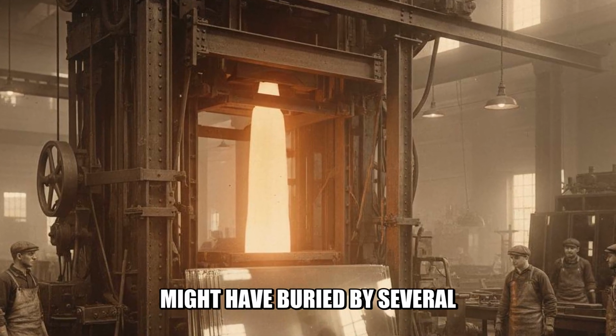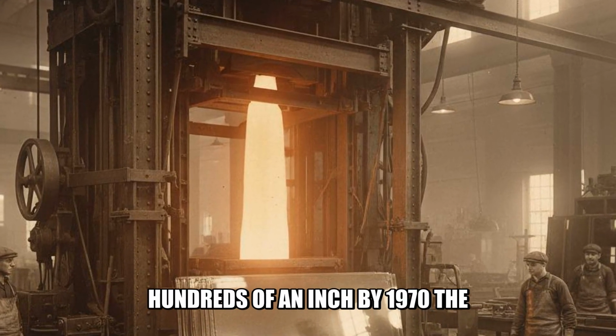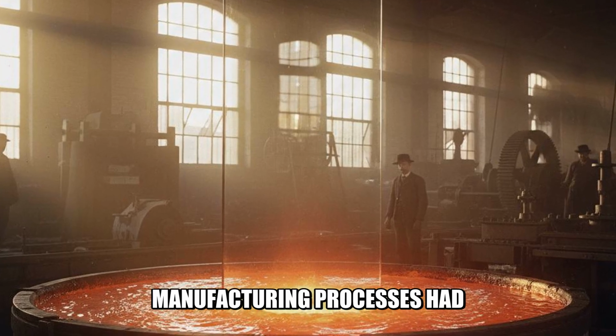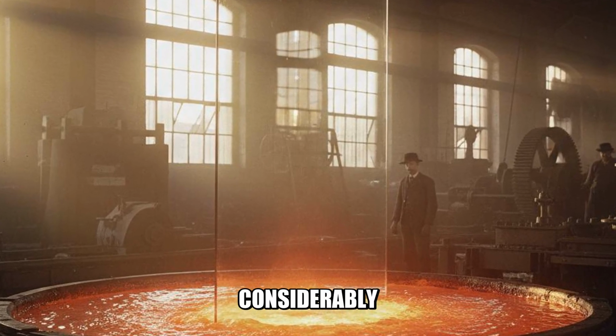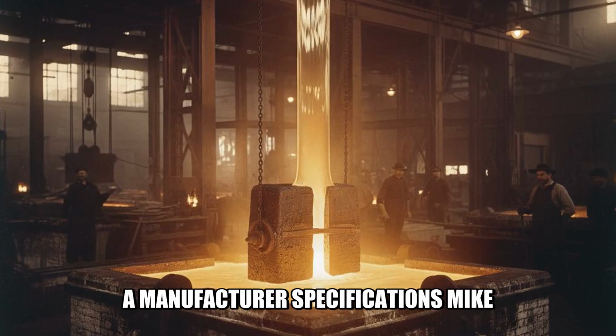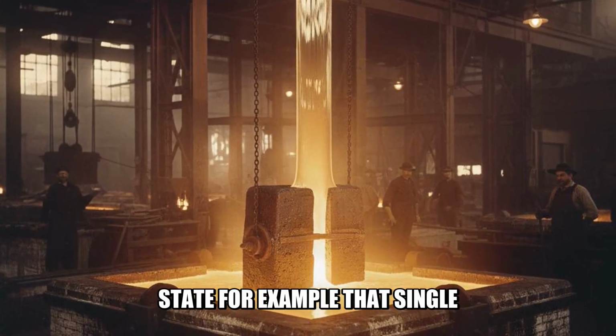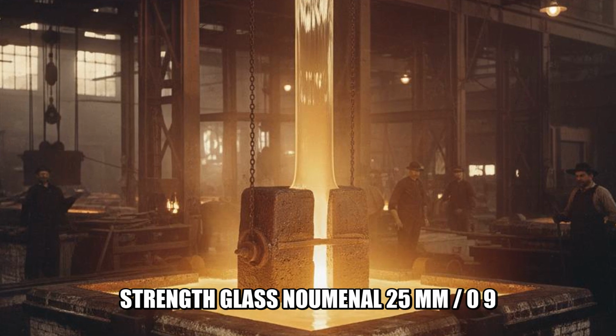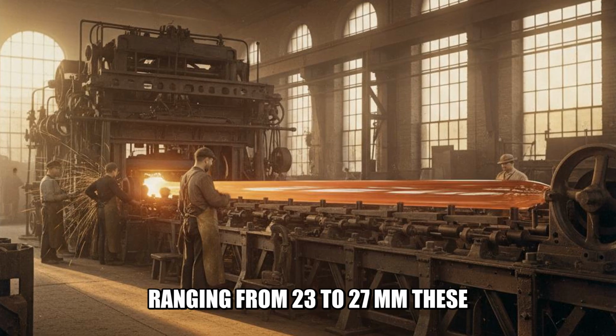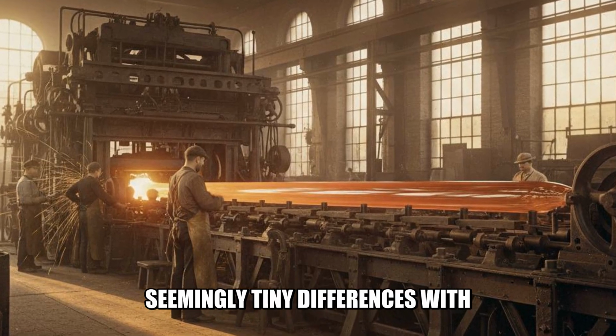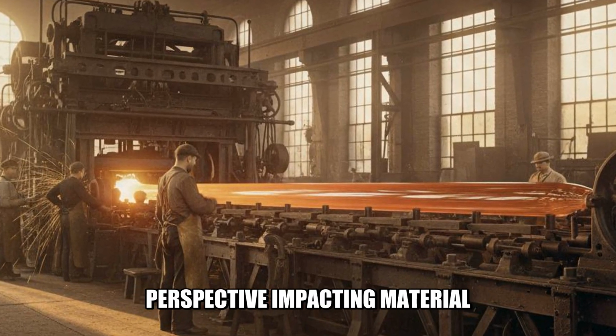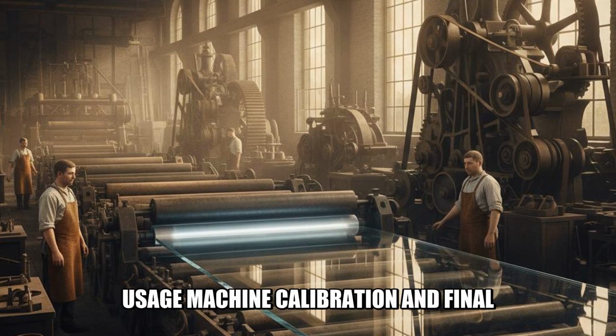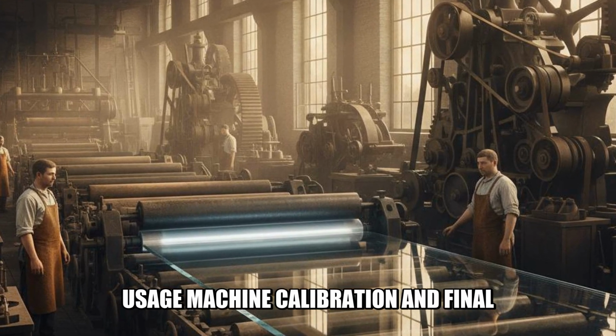Early in the century, a single-strength pane might have varied by several hundredths of an inch. By 1970, the manufacturing processes had tightened these tolerances considerably. A manufacturer's specification might state, for example, that single-strength glass, nominal 2.5 mm or 0.098 inches, would have an actual thickness ranging from 2.3 mm to 2.7 mm. These seemingly tiny differences were significant from a manufacturing perspective, impacting material usage, machine calibration, and final product quality.